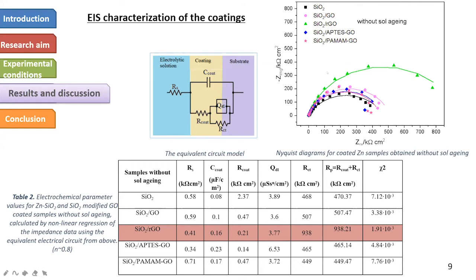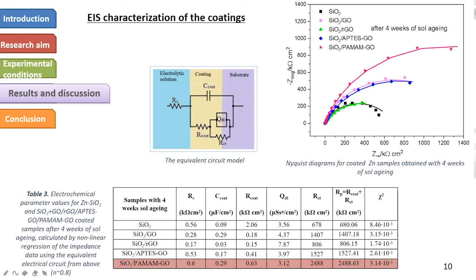It was a surprise for us that without soil aging, the silica containing RGO sample had the best result. Here we can see on the Nyquist diagrams. To be honest, we couldn't find a great explanation for this. The rest of the coatings have similar polarization resistance values. On this slide, we can see the details.